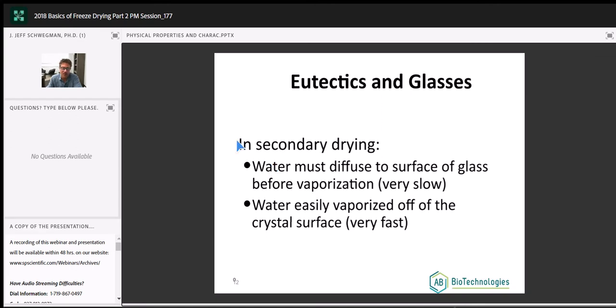Okay, secondary drying for the amorphous phases. Water must diffuse to the surface of the glass before vaporization. Very, very slow process. We can actually damage our product or collapse the product on our ramp to secondary drying if we're not careful. Very differently with crystalline, at the end of primary drying for a completely crystalline formulation, we're already 99.99% dry.